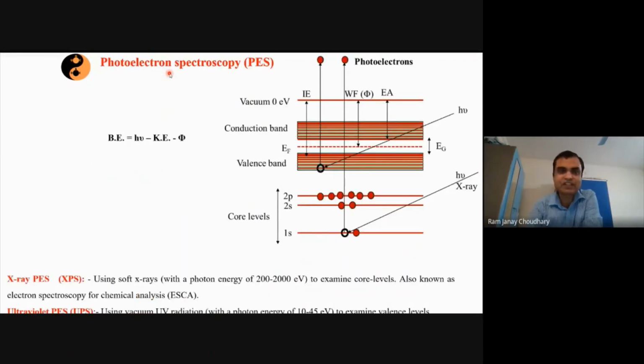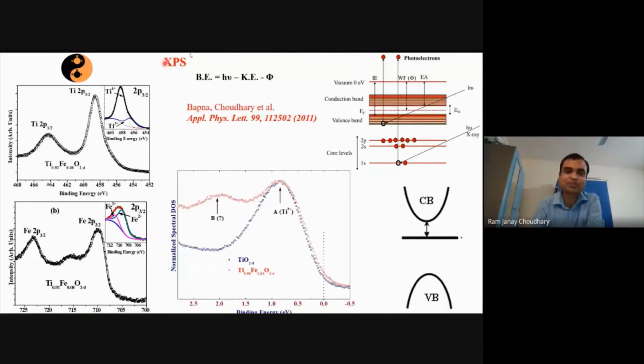And from here you can see that we did this X-ray photoelectron spectroscopy, and from there you can quickly see the charge state. How do we calculate the charge state? We calculate it by understanding the binding energy. For different charge states of elements, the binding energy of electrons differs, right? So if iron was in a metallic cluster, then this peak should occur at 706 electron volt. But what you see is that the peak is occurring at about 709 electron volt, right? So from there one can confirm that iron is not present in the metallic state, rather it is present in some kind of charge state, right?